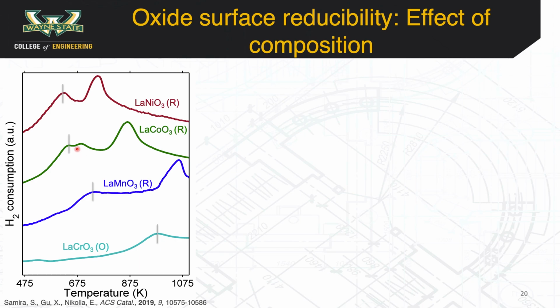We then go on to study the effect of the B-site composition while varying the B-site all the way from nickel in LaNiO3 to chromium in LaCrO3. What is observed is as one moves from nickel to the left of nickel amongst the 3D metals, it becomes challenging to reduce the oxide, as indicated by an increase in the oxide surface reduction temperature.